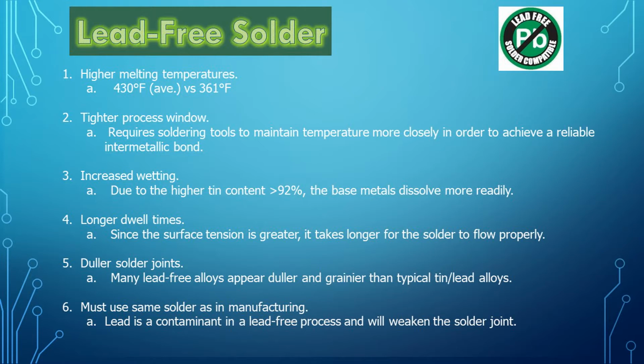Melting temperatures are higher, the solder has a higher surface tension, and does not flow as easily as tin lead. It also has a greater ability of dissolving copper and iron-plated soldering tips because of the high, greater than 92% tin content. These materials are typically more challenging to use, and the solder joints tend to be heavier and more grayish and grainy in appearance, so we must be aware of this and must learn how to make and inspect these connections.